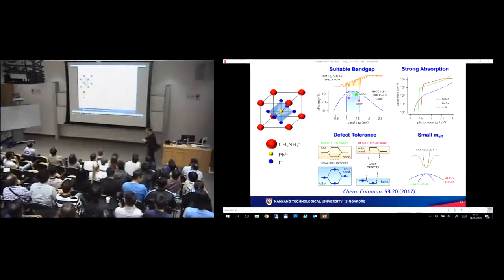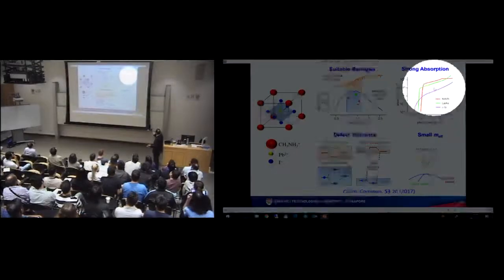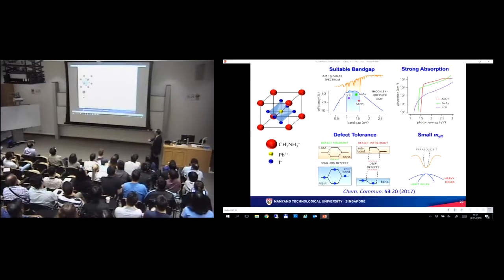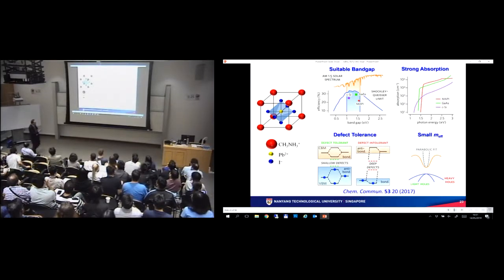Now, apart from that, perovskite seemed to hit it right. It has a very suitable band gap, in the range that is most useful. It has very strong absorption, stronger than your gallium arsenide and your silicon. And it has very good defect tolerance, because of the nature of the band structure. The states are formed by antibonding states, the top of the valence band and the bottom of the conduction band. Now, this resulted in very shallow defects being formed. Because these shallow defects are easily filled, they are termed very benign. In contrast to typical systems where you have deep defects, which would cause you a lot of problems in terms of purifying the material. So that's why it is a very special combination of traits that gives perovskite this very unusual property.